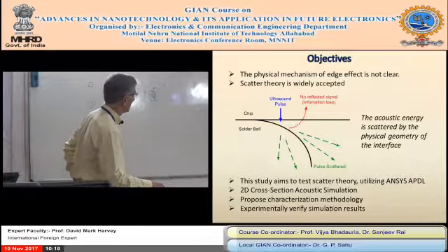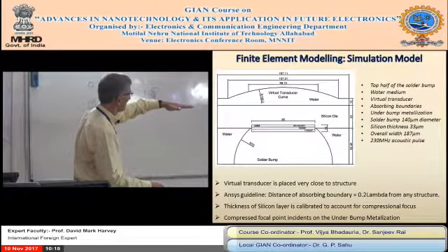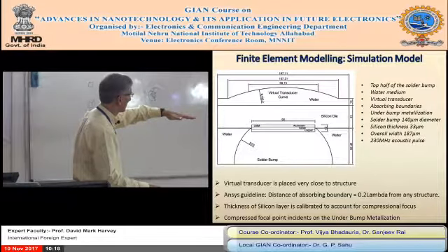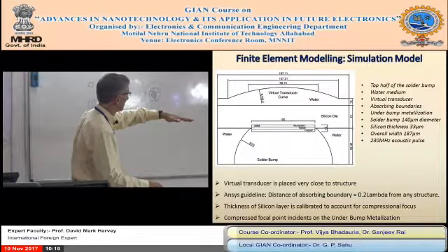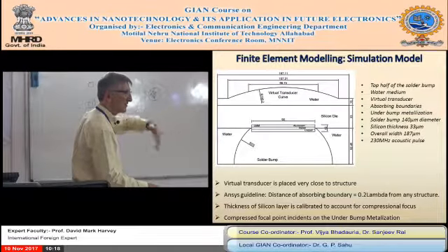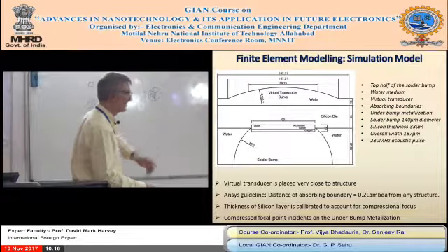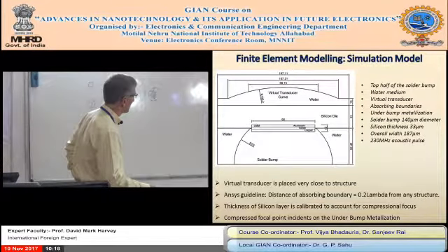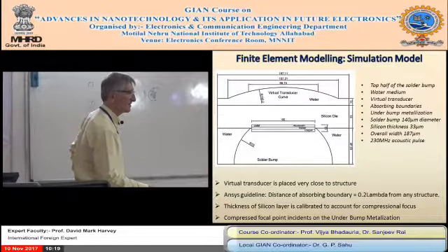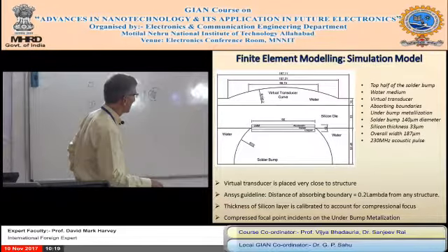So it comes through the silicon die. As I said, the silicon die is a flip chip. Then there's underbump metallization, aluminium, nickel and copper, I think, before you attach the solder joints. It's got to go through those layers as well. So all these factors have to be entered in. There's a solder bump. R70 means it's 140 microns diameter. And there's the water. And we're ready to go.